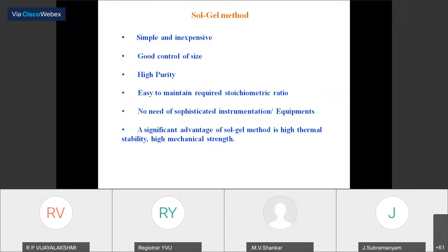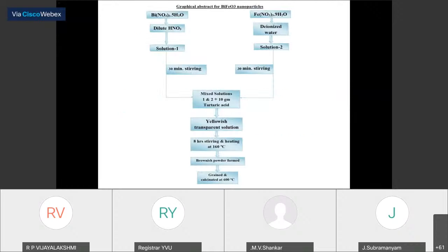In the sol-gel method, we have the gel in terms of the solution. How do we get the gel? We have the liquid, and the process here is hydrolysis and condensation. That is the case in the sol-gel method. Here in our lab, we synthesized bismuth ferrite oxide nanoparticles by using the sol-gel method. So what did we notice as far as bismuth ferrite oxide is concerned? We synthesized it by the chemical co-precipitation method, and we also synthesized it by the sol-gel method.